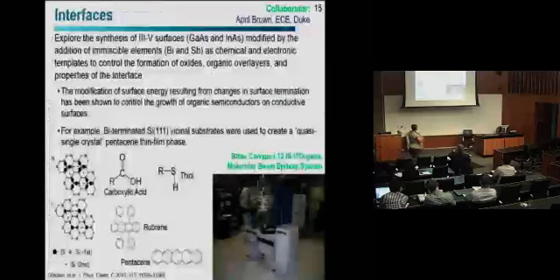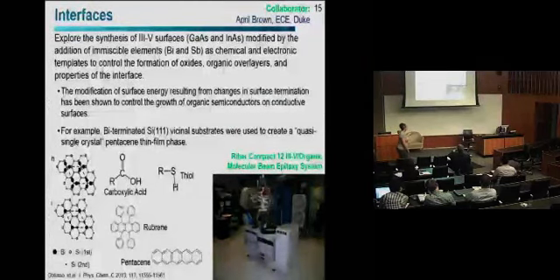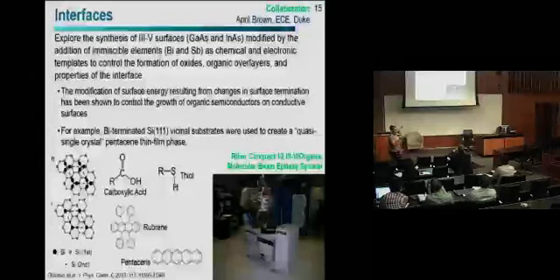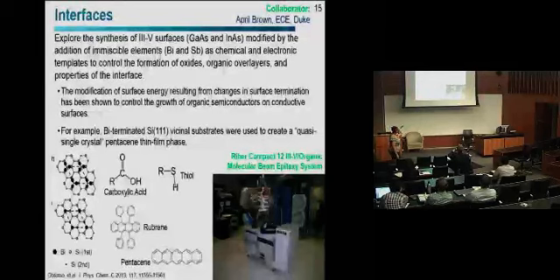Another example is some work we're starting to do with April Brown that takes me back to my original love of MBE, molecular beam epitaxy. But again, looking at this idea of hybrid organic-inorganic materials, and in this case, interfaces, where you can have unique surface terminations by introducing bismuth elements into a III-V semiconductor surface, and then looking at how they and their oxides interact with different types of molecules and small molecules. And so using molecular beam epitaxy to do that, as well as interaction with the RIR-MAPLE. And this could be something that enables unique sensors, for example, by having these functional interfaces that you can control.